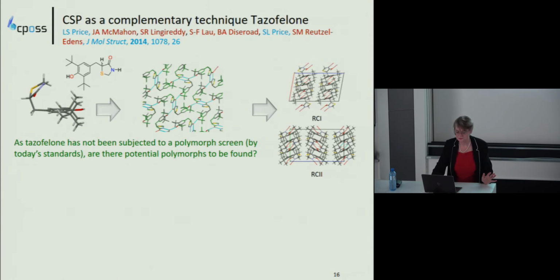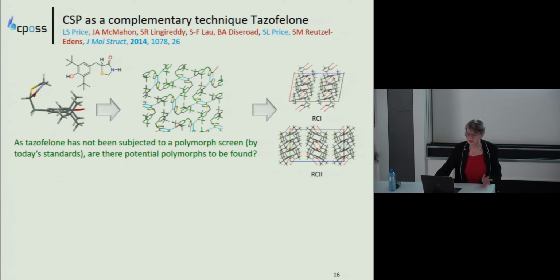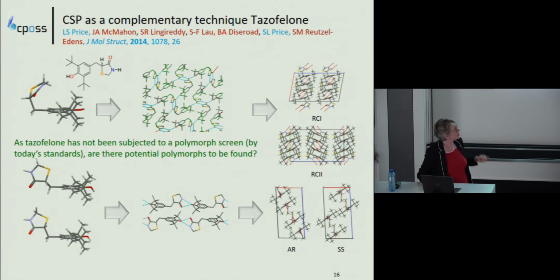organic polymorphism pharmaceuticals. So here's one drug, Tazofelone, which is chiral. You can see the hydrogen there. When we went into it, Eli Lilly had done some screening over a decade ago and knew 2 polymorphs for the racemic form, which had the same hydrogen bonded layer but stacked in different ways. But they'd also done the structure that the enantiomer pure crystal had 2 different conformations in its unit cell.